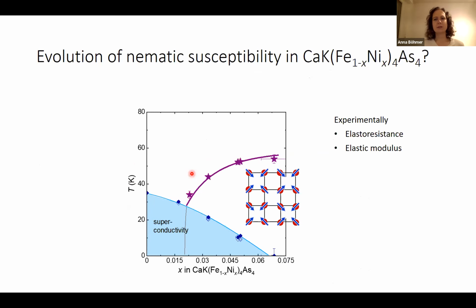But what we were wondering is what will this look like experimentally? So here's our phase diagram again, and I want to emphasize this is a large phase diagram. We go from a Tc of 35 to fully suppress the magnetic order. There is no orthorhombicity, there is no nematic order, there is no stripe type magnetic order. So here we are fully tetragonal, and we were still wondering what's the nematic susceptibility in this fully tetragonal phase diagram. And we are looking at elastoresistance and elastic modulus measurements.